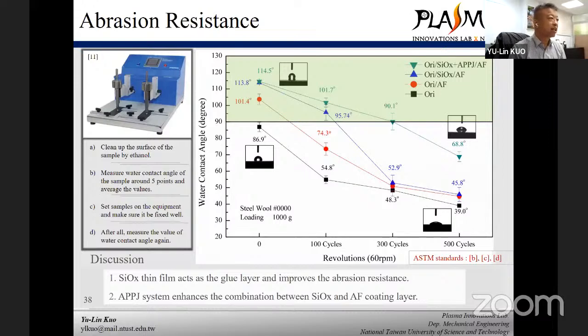But if you put some silicon oxide coating on the surface as a tiny thin layer, as you can see, a super hydrophobic surface can be obtained, around 114. After 100 cycles of abrasion, it will dramatically decrease, but it's still higher than the standard. So if you only use this process, you still can have the 100 cycles performance. However, we try to have better performance. As we can see in the green one, if you apply the plasma onto the silicon oxide, you can reach 300 cycles, because we can still achieve 90 degrees, the industry standard.